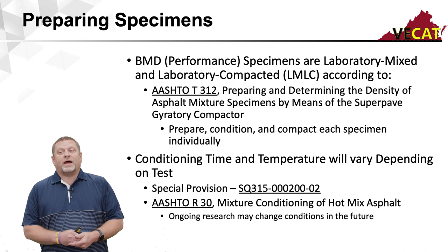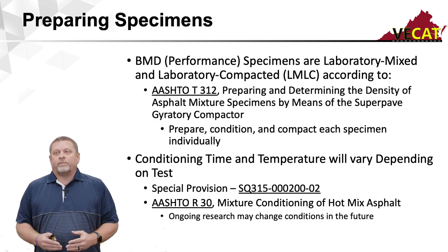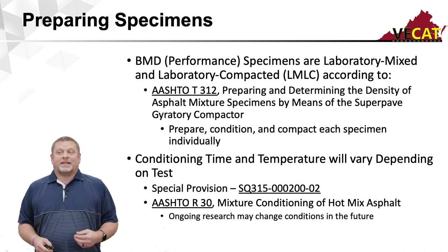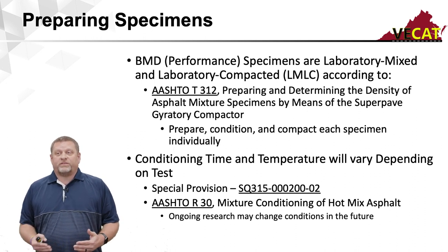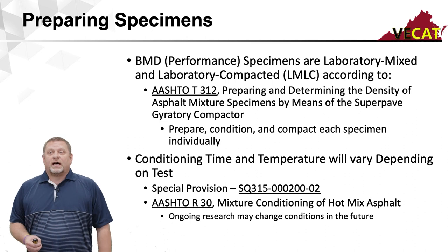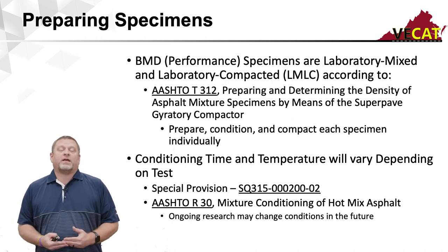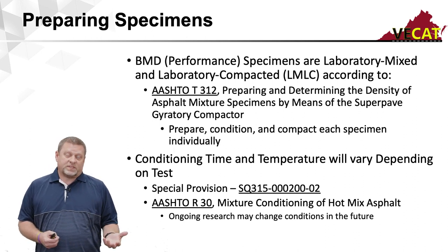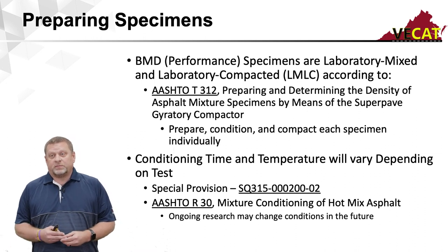Let's start talking about how we're going to handle these specimens. Every one of them is a little bit different. The BMD specimens will be laboratory mixed and laboratory compacted according to AASHTO T312. That's the way it's always been in the volumetric phase, volumetric design. Basically, it tells us how to prepare our specimens, how to condition them, and how to compact them individually. So that applies whether we're making a performance test or BMD test specimen or our normal volumetric specimen.